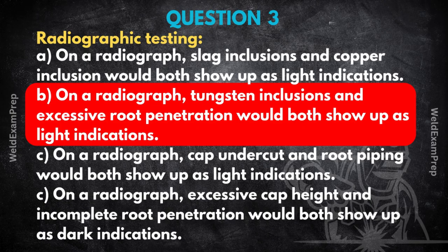Exactly. And areas that are less dense or thinner, like porosity or lack of fusion, let more radiation through, appearing darker. So tungsten is a very dense metal, much denser than steel. It absorbs a lot of radiation, shows up light. And excessive root penetration means extra weld metal sticking through, making that section locally thicker. More thickness, more absorption, so it also appears light.